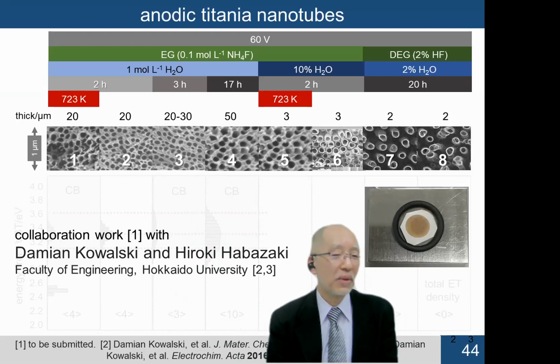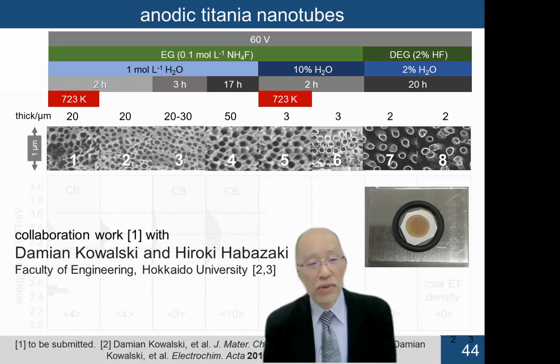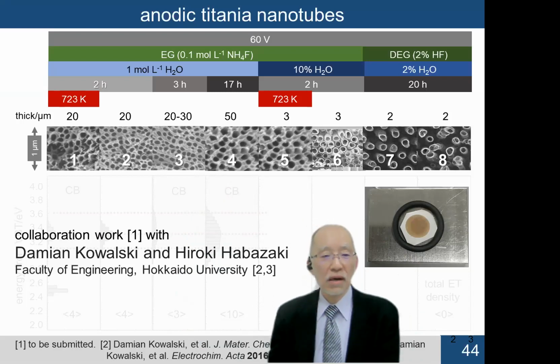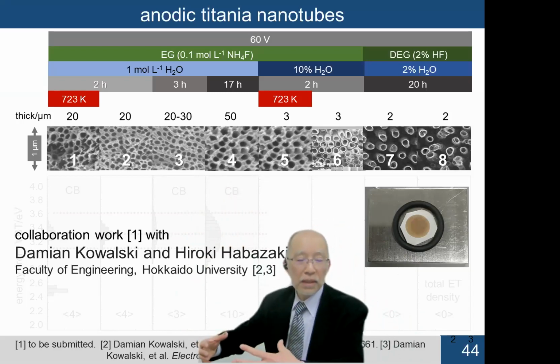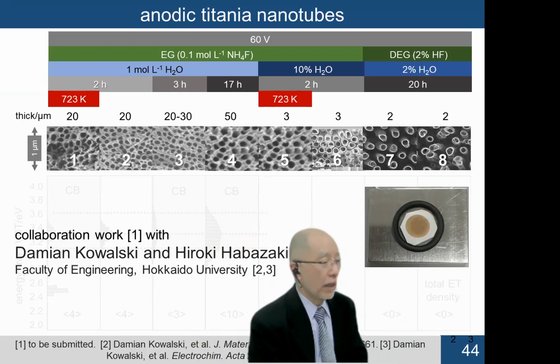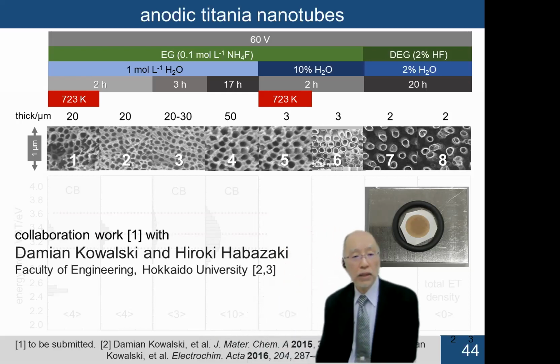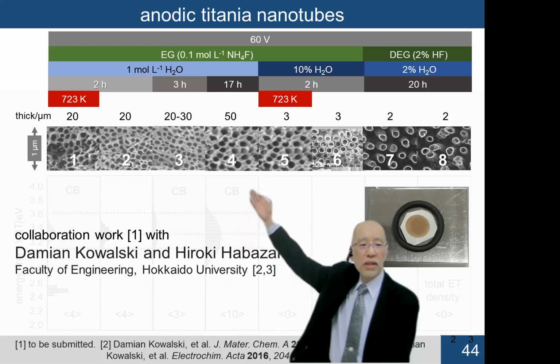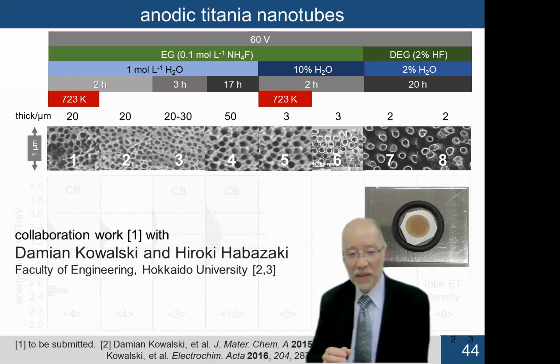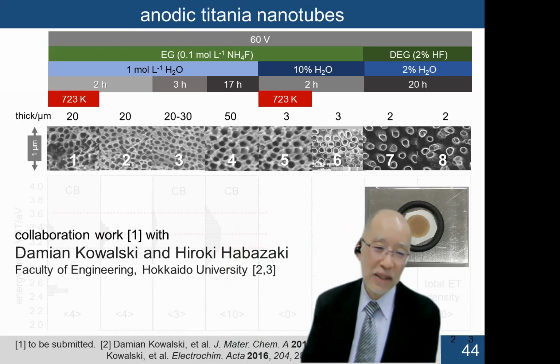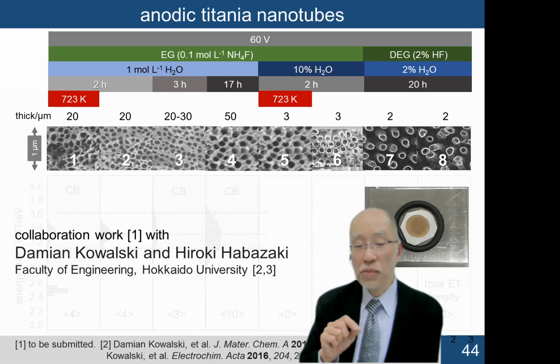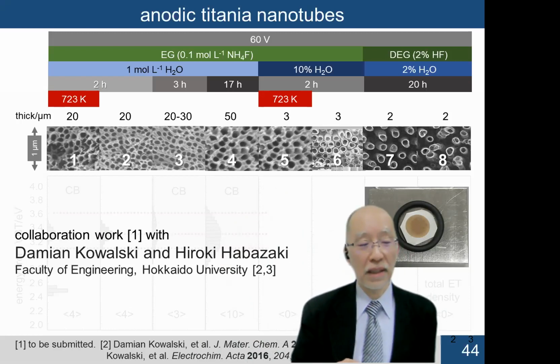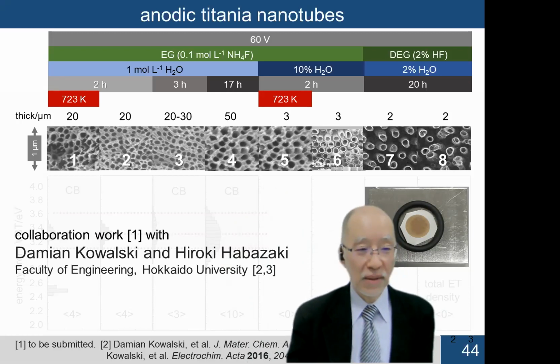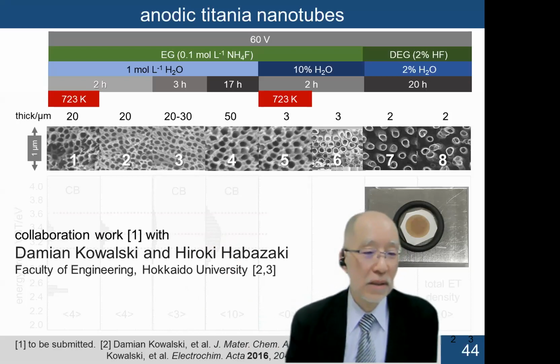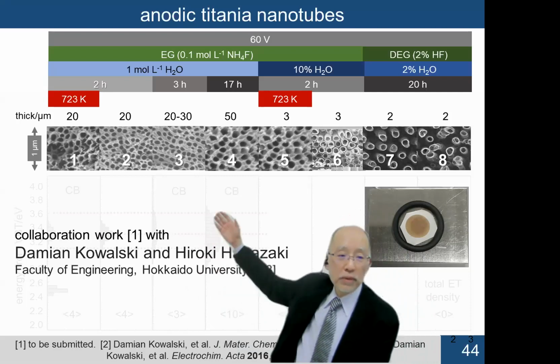Because there is almost no analytical method to determine the structure of a nanotube, you only know the size of the pore, the length and the density, checked by SEM, scanning electron microscopy. Since it is prepared from titanium metal, it might be titanium oxide, TiO2. But XPS, X-ray photoelectron spectroscopy, only tells that it is similar to TiO2. And there is no XRD peak, so it is almost amorphous, and it is impossible to get any structural information except for this same picture.